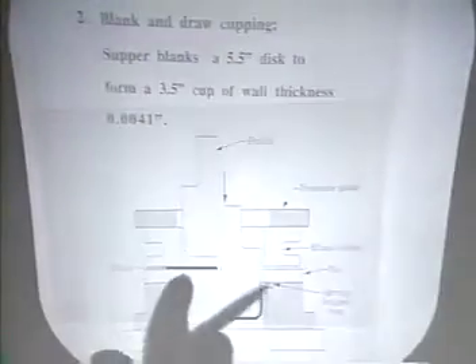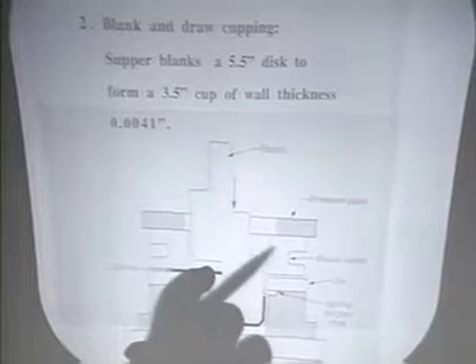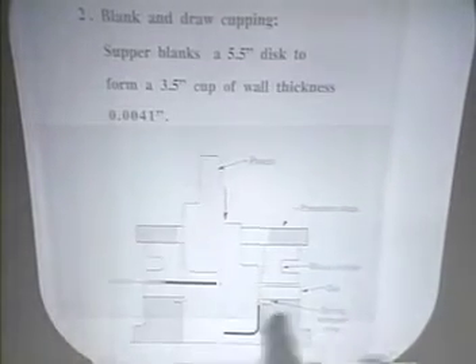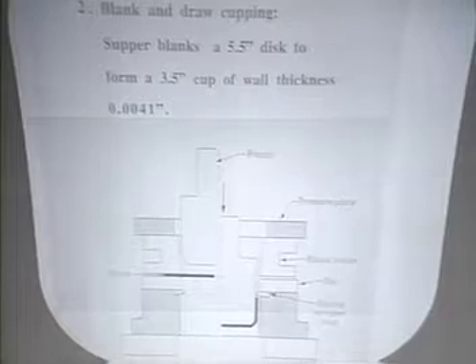So what happens then, this blank, this 5.5 inch disc forms a 3.5 inch cup. Here it is, and here's the wall thickness of 0.0041 inches. And this is what it looks like, kind of. There's a punch, quite literally. Here's the blank, the flat 5.5 inch disc. This punch comes down and pushes it into this shape, stretches it into that shape. Okay? Okay, now, we still don't have a whole aluminum can here.